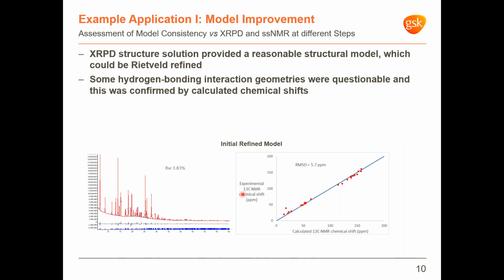As I mentioned, we could in this case identify with some confidence a convincing structural model out of the XRPD structure solution step and successfully refine it. Having said that, some hydrogen bonding distances and angles were slightly off range and clearly susceptible of improvement. I am showing here the refinement of the initial model, which does look quite good. And on the right, the consistency between calculated chemical shifts from the refined model and the experimentally measured ones from solid-state NMR. Maybe 1 or 2 slight deviations can be observed, but overall this doesn't look too bad either.